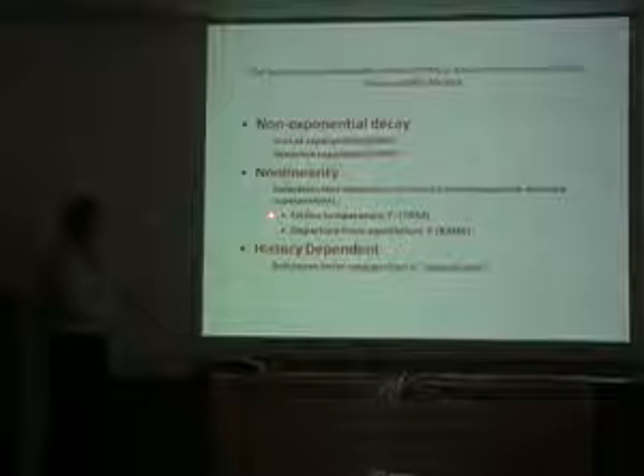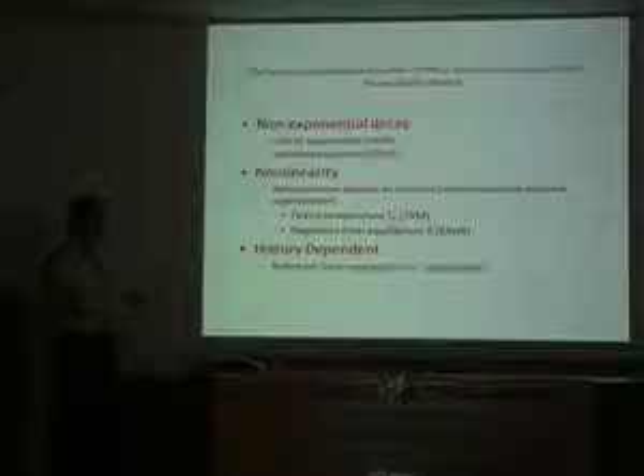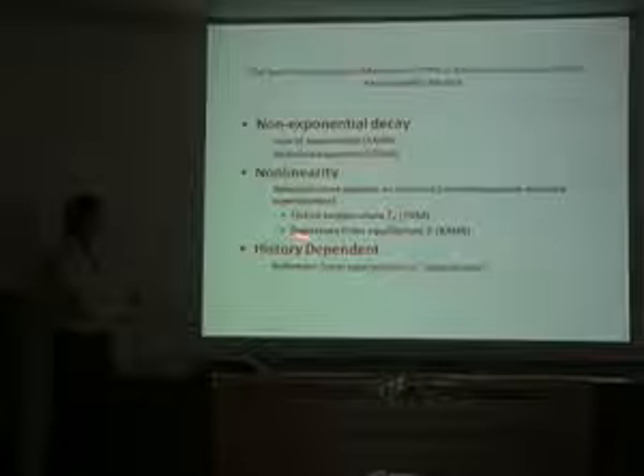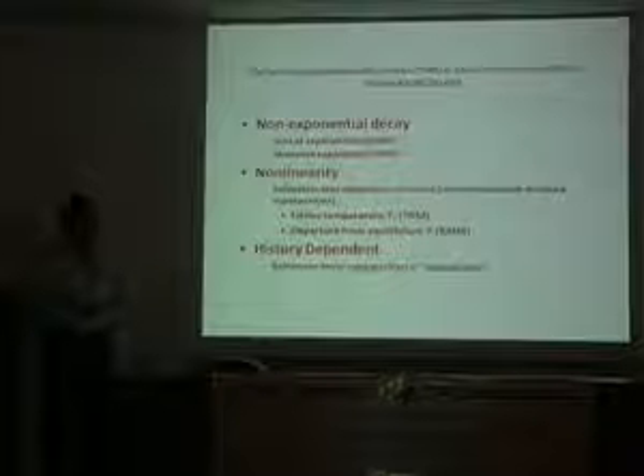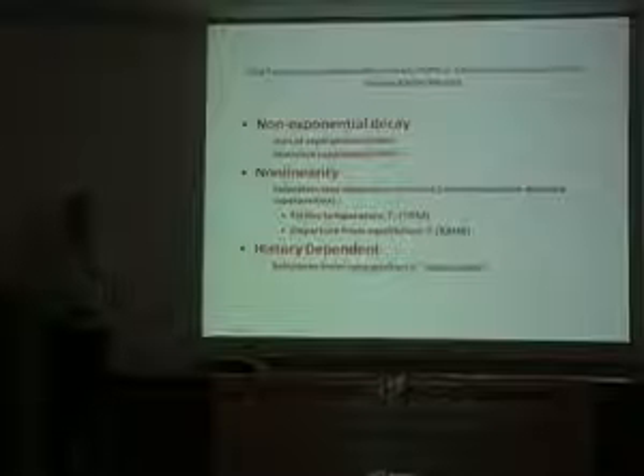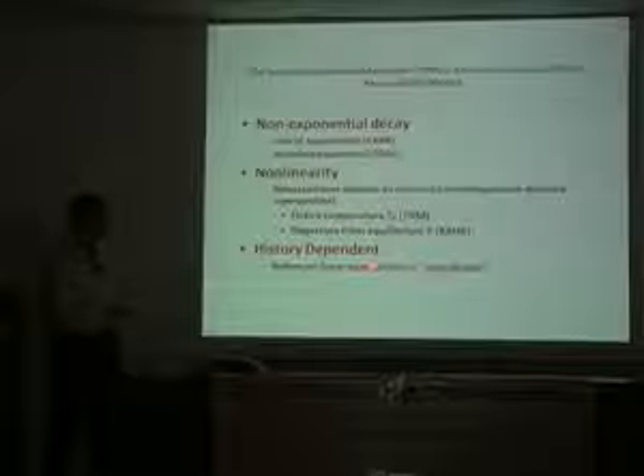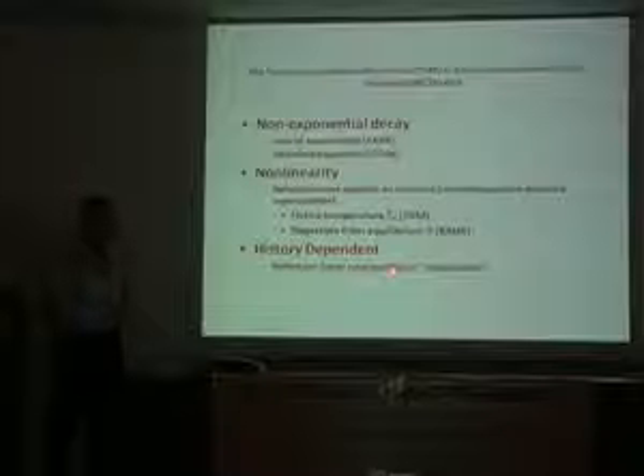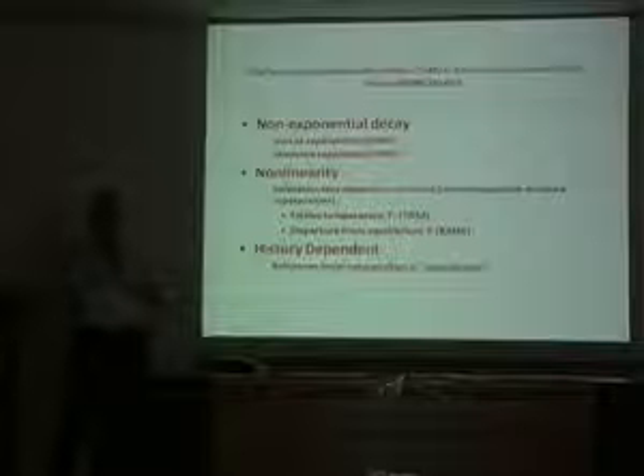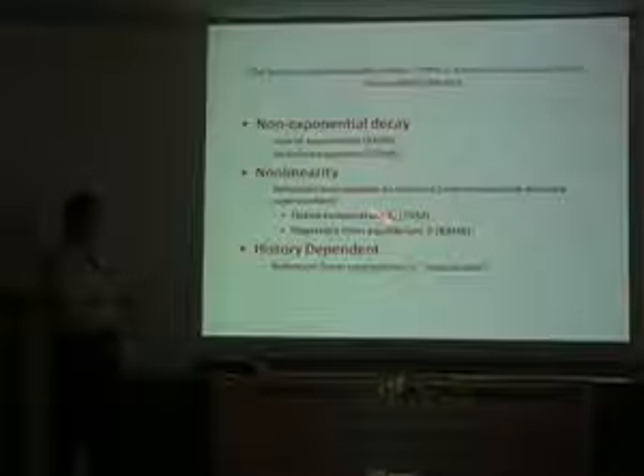Okay? So the TNM model uses a fictive temperature as a measure of structure. The KAHR model uses a departure from equilibrium delta as the measure of structure. And you need some sort of history dependence, which can describe the memory effect. And they choose that you have Boltzmann superposition for these temperature histories in what they call reduced time or internal time, okay, which is related to this nonlinearity parameter. And I'll show you what the equations look like now.